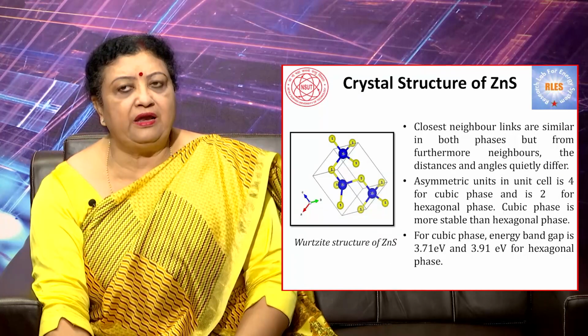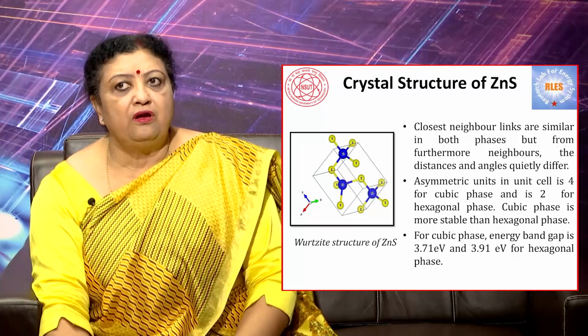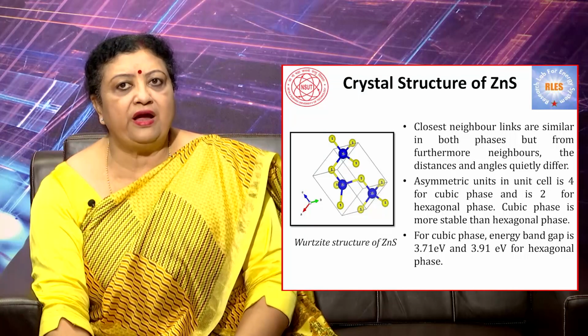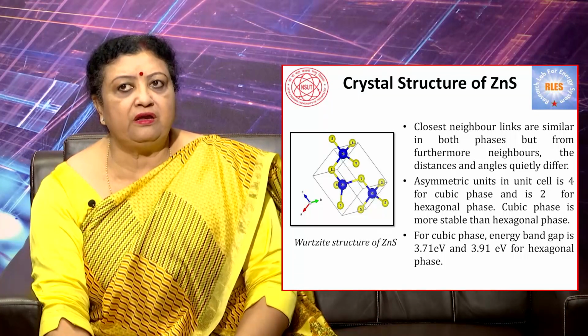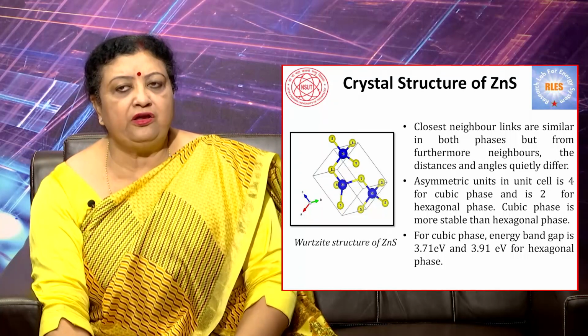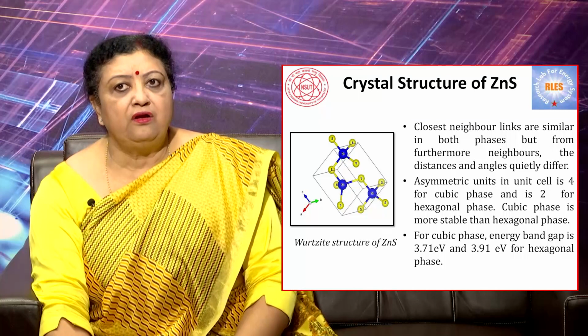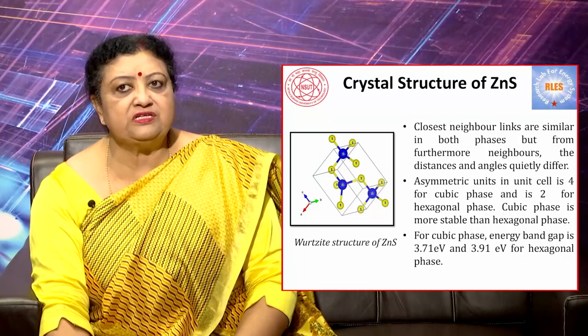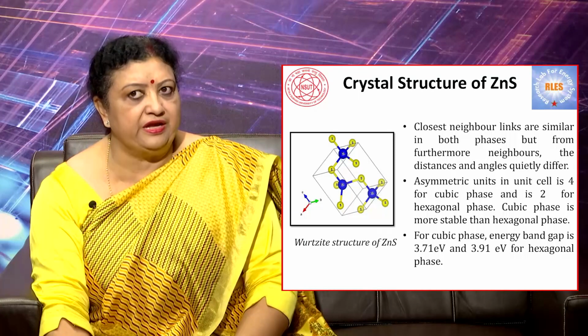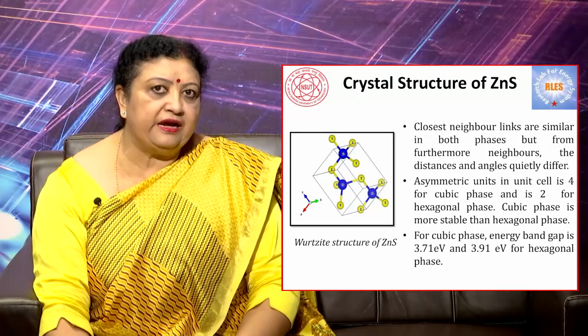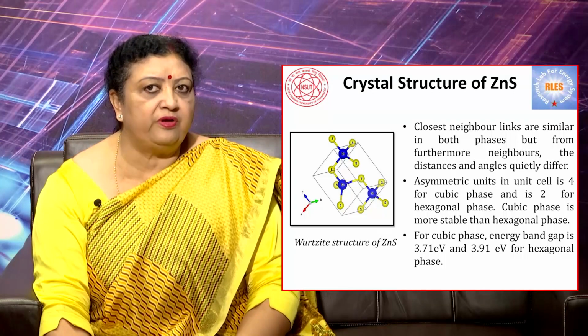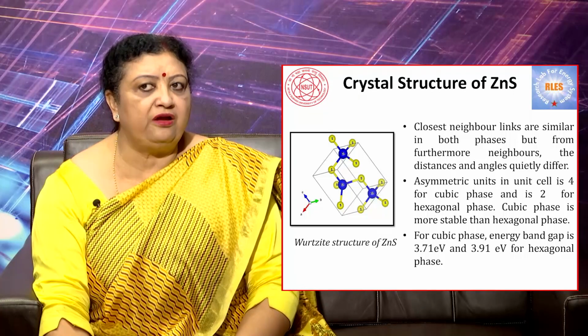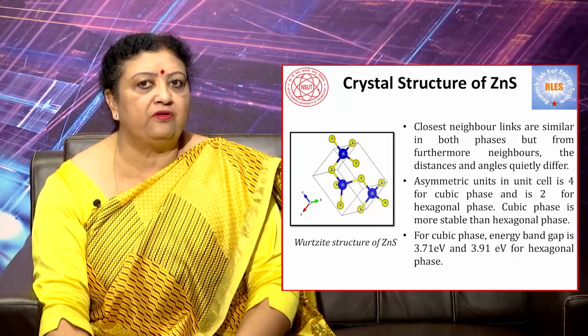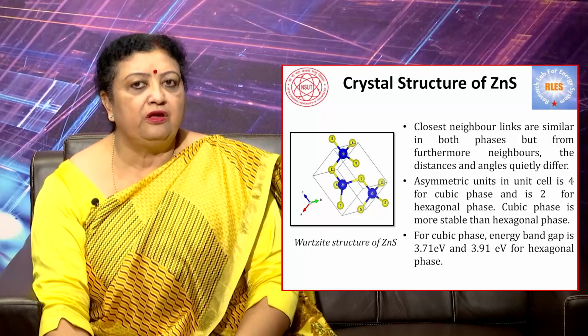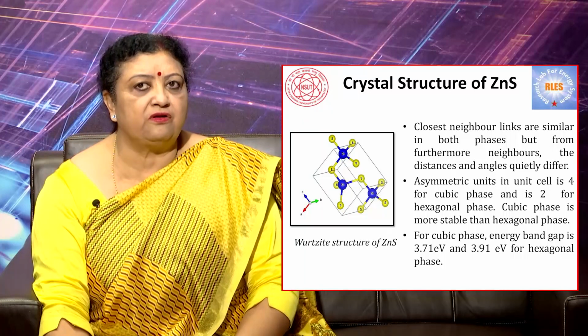Closest links are similar in both phases, but from farther neighbors the distances and angles quietly differ. The asymmetric unit in the unit cell is 4 for the cubic phase and 2 for the hexagonal phase, and the cubic phase is more stable than the hexagonal phase. The energy band gap is 3.71 electron volt for the cubic phase and 3.91 electron volt for the hexagonal phase. Here in this picture, you are able to see the wurtzite structure of ZnS.